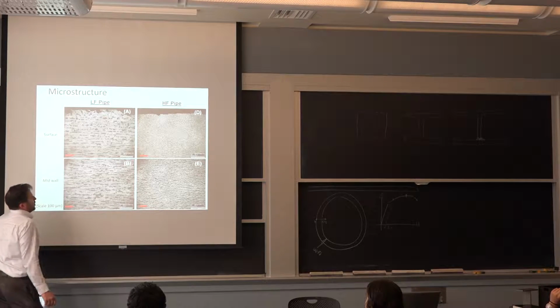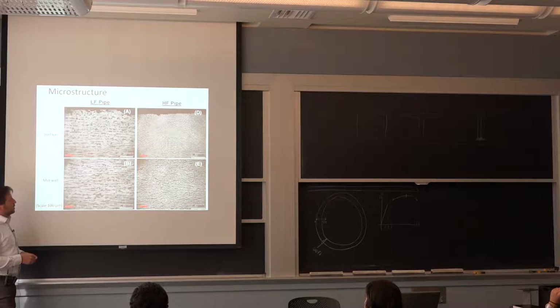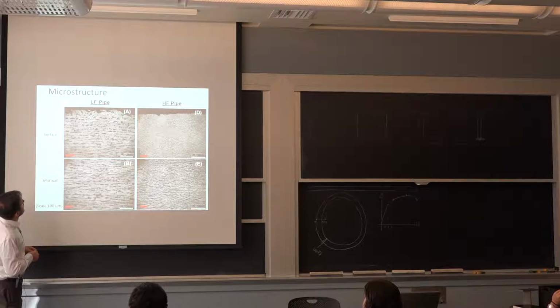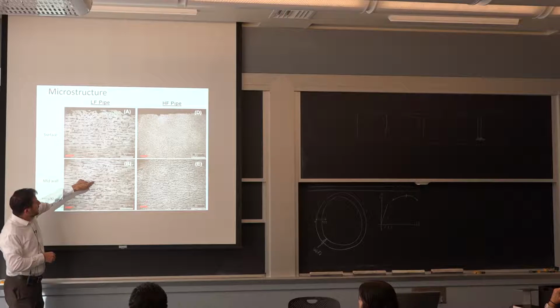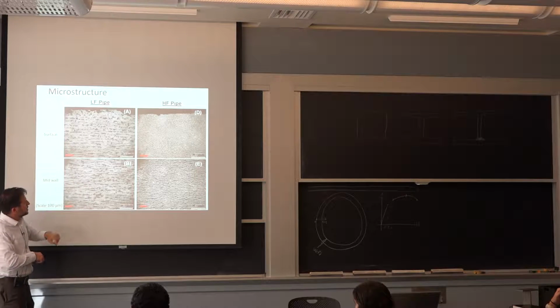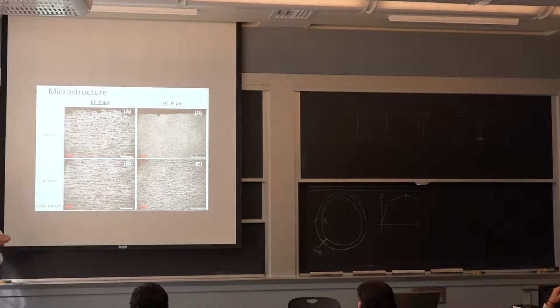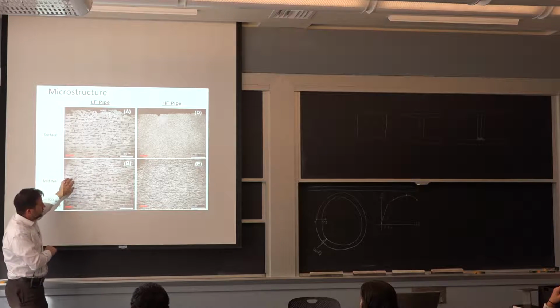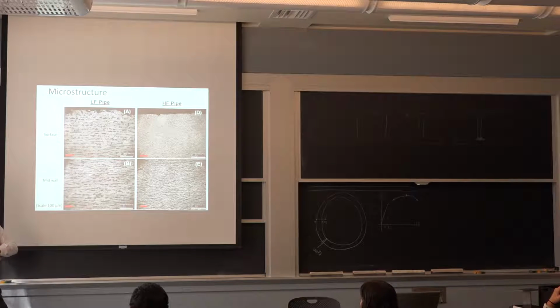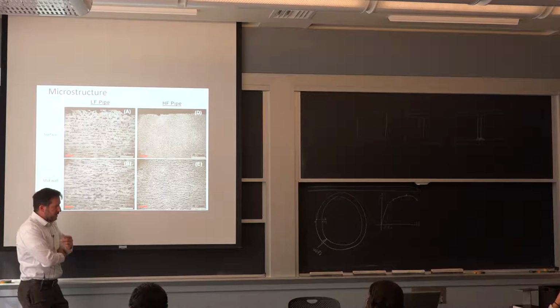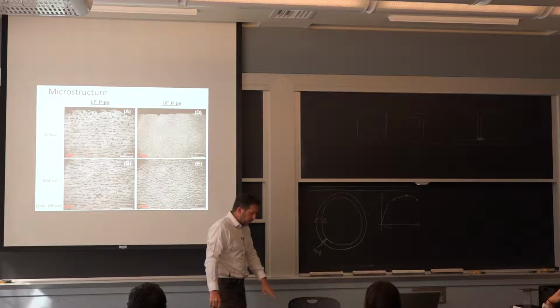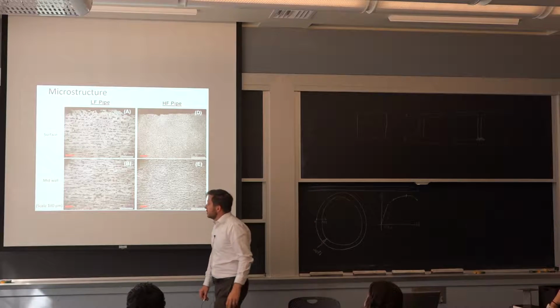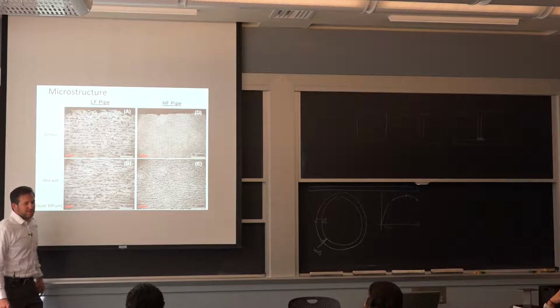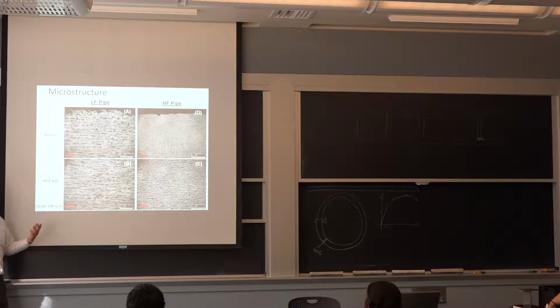So we'll go through heat treatment in the next lecture. We're going to start that on Thursday, but you see a little bit of the black zone, that's the pearlite, and some of the white zone is essentially the pure iron. If you look at that microstructure on the surface as opposed to mid-wall, it's just about the same. So the fact that we were getting different properties cannot really be explained by a change in microstructure. Now, I think you guys realize when we do the cold deformation, we're changing the dislocation density, but we're not changing how it looks under the microscope, because the dislocation is so small, you can't see it.